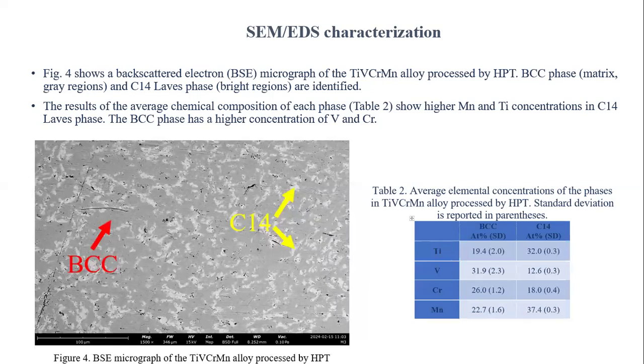In the SEM and EDS characterization, the micrograph of the titanium, vanadium, chromium, manganese alloy processed by HPT shows BCC phase as the gray matrix regions and C14 Laves phase as bright regions. The results of average chemical composition of each phase show higher manganese and titanium concentrations in the C14 Laves phase, and the BCC phase has higher concentrations of vanadium and chromium.